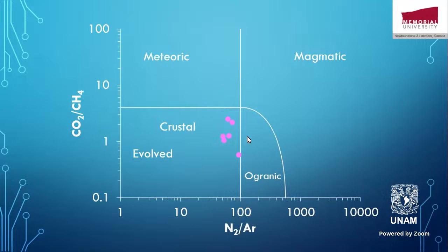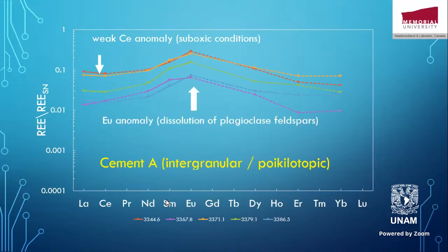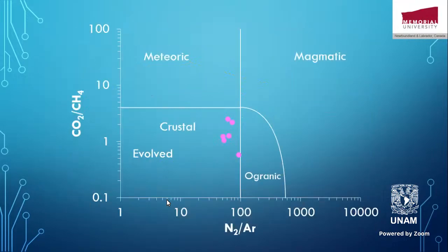We apply the same idea of the gas ratios to those cements. And in this case, we are dealing here with cement A, not cement B. Cement B was fracture filling cement and was very rare. So the majority was the intergranular cement. And you can see, they are crustal or evolved crustal fluids. So it means that they were like a mixture of those marine water threading between the grains and the meteoric water, because it's a fluvial marine environment.